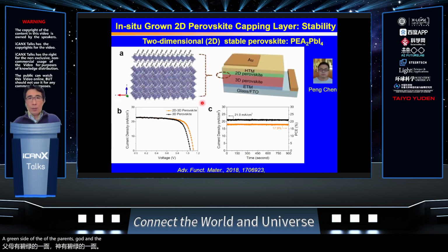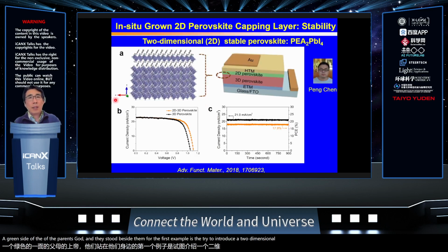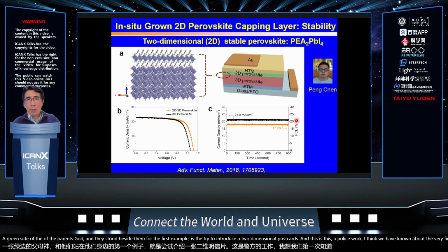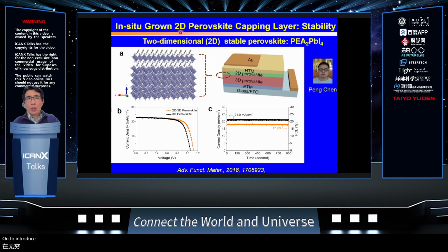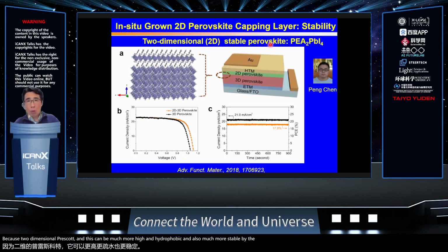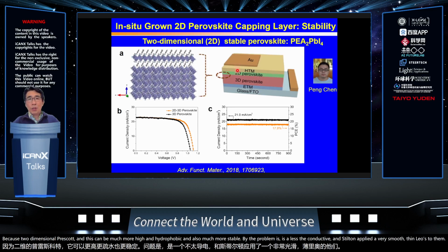And so, for example, the first example is to try to introduce a two-dimensional perovskite. In Peng's work, I think we were one of the very first to introduce the two-dimensional material on top of three-dimensional perovskite, because two-dimensional perovskite can be much more hydrophobic and also much more stable. But the problem is it is less conductive. So Peng applied a very thin layer of two-dimensional material on top of the 3D to protect the material.